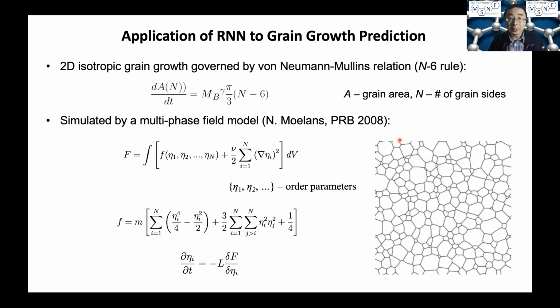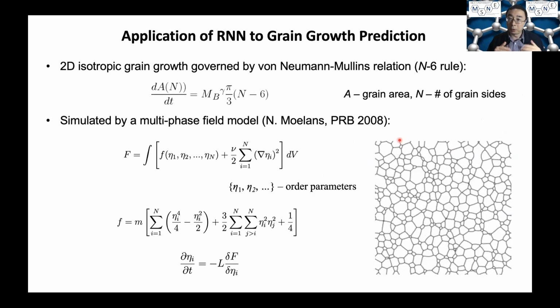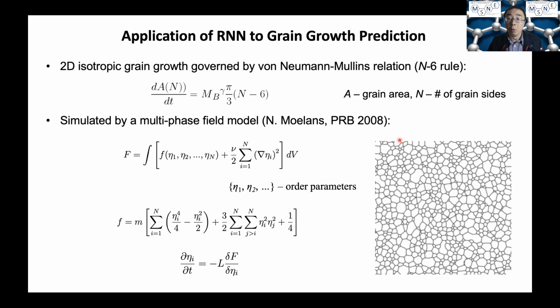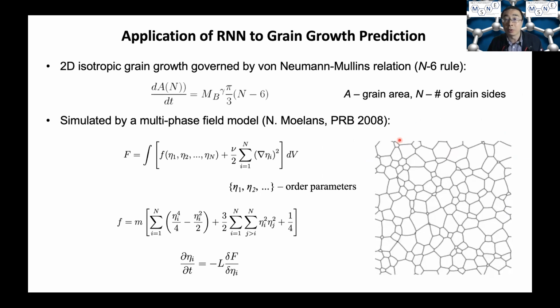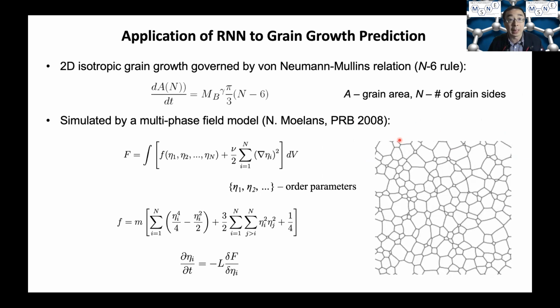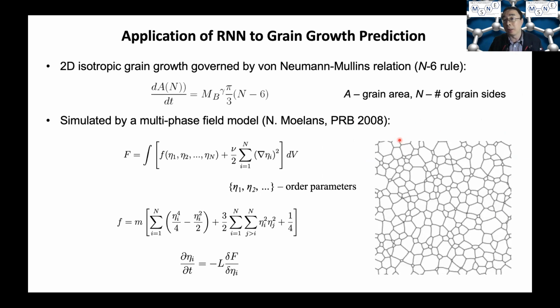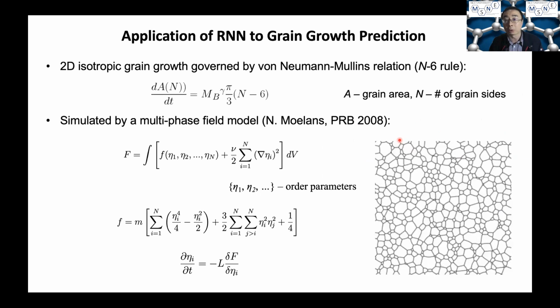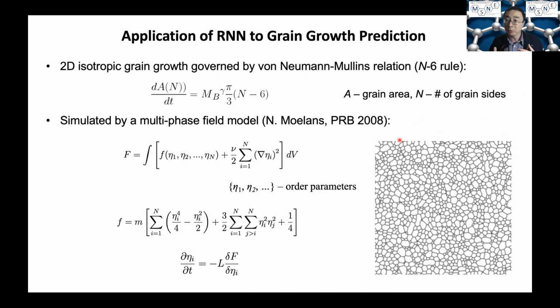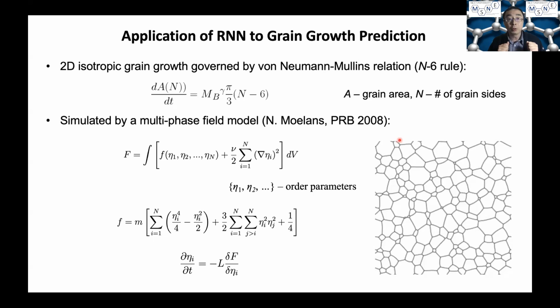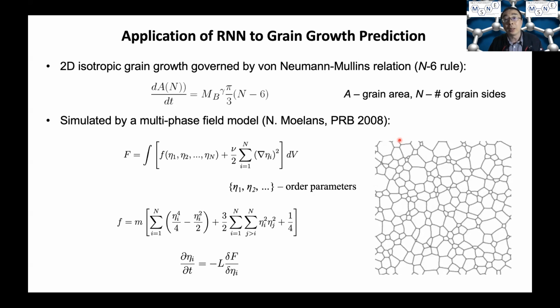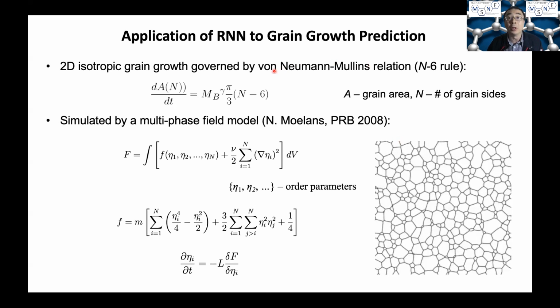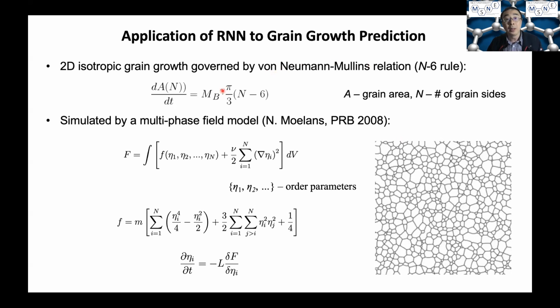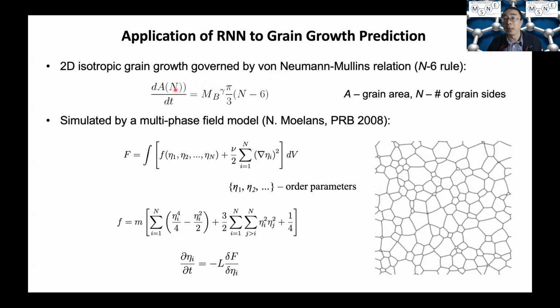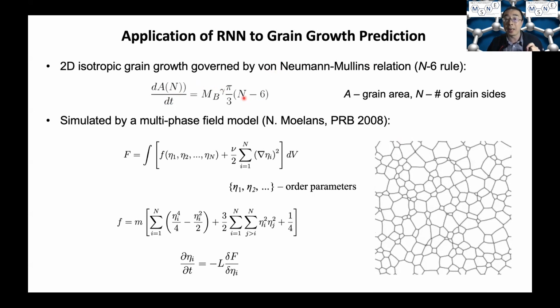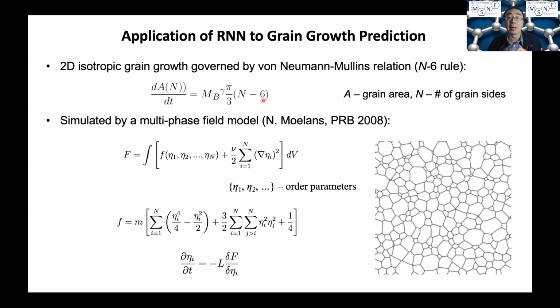We're very excited by this discovery, and then we further applied this technique to more realistic microstructure evolution phenomena. One example we look at is the grain growth kinetics. The physics of grain growth is well understood. It happens in polycrystal structures at a relatively high temperature when the atoms are mobile, which can cause the grain boundaries to move. For a two-dimensional isotropic system, the grain growth kinetics is governed by the well-known von Neumann-Mullins relation, which says the rate of area change of a grain is controlled by its number of sides n minus 6. This is also known as the n minus 6 rule.